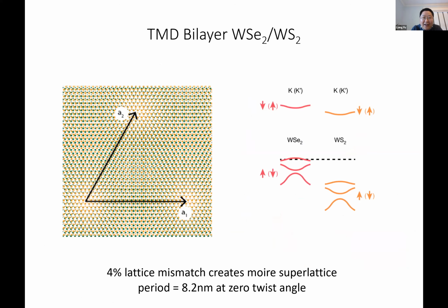Okay, so I'm going to describe the Moiré superlattice out of these TMD materials. This can be made, for example, by taking 2 different materials with a lattice mismatch. So in this example, this is tungsten diselenide and tungsten disulfide. They have a 4% lattice mismatch. So without any twist angle, aligned WSe2 and WS2 already naturally form a Moiré superlattice. And in this case, the Moiré period is about 8 nanometers.